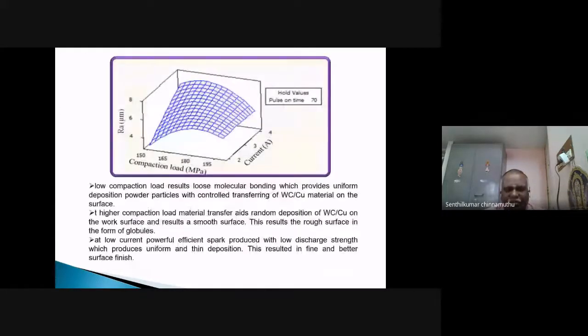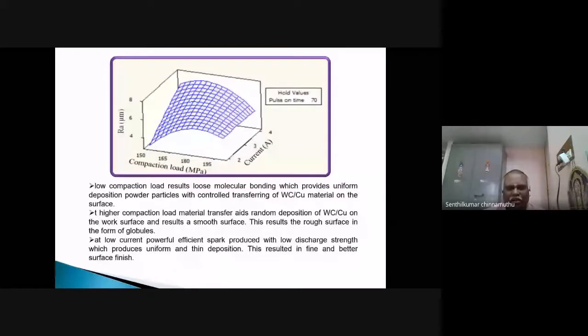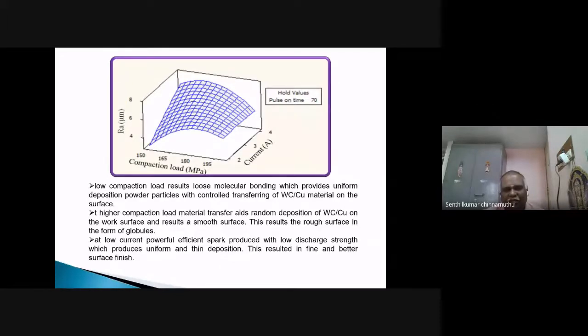The surface roughness. The effect of compaction load and current on surface roughness. The surface roughness increases with the compaction load. Why? Because at lower compaction load, the surface roughness is very less. The surface roughness is uniform, because more material is disintegrated and it is deposited on the surface uniformly. But whereas in the case of higher compaction load, the bonding between the material is very high, so that the material is deposited non-uniformly on the surface at the higher compaction load. So random deposition takes place.